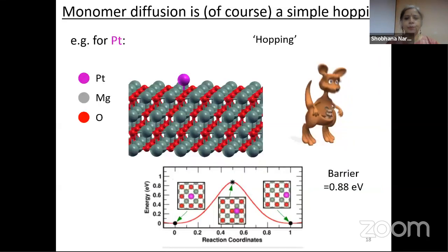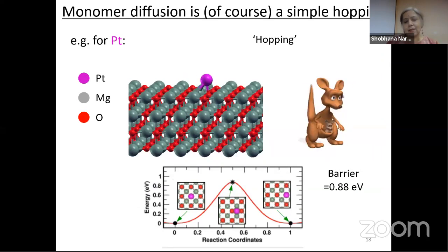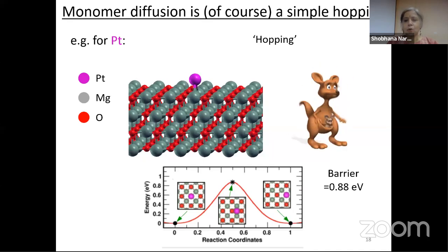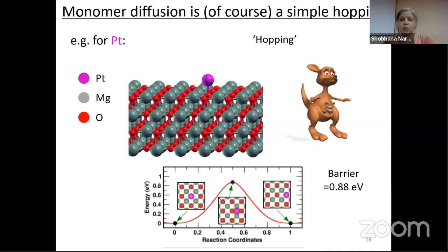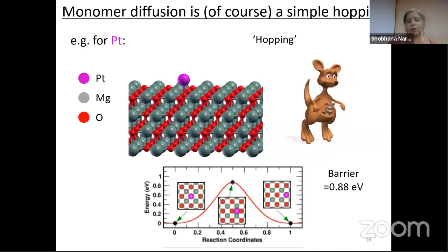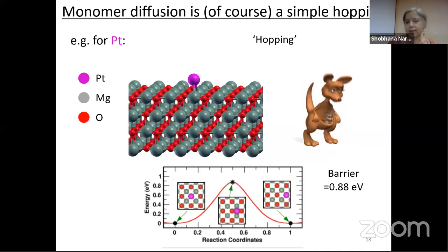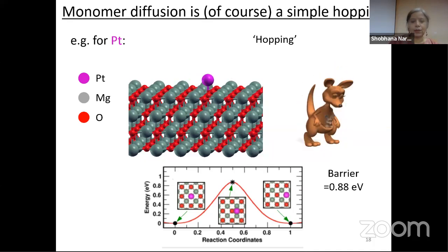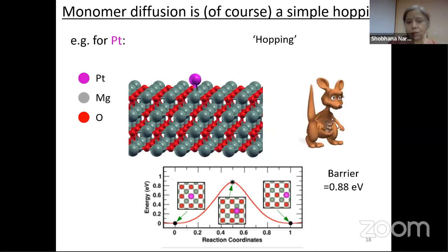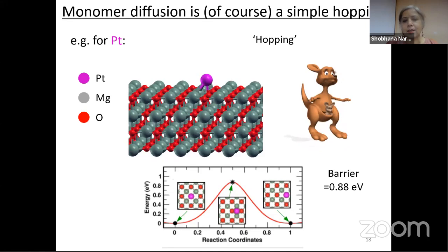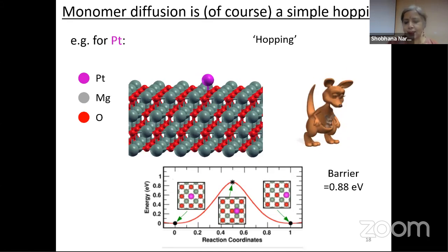Let me show you. So if you have a monomer, there's only one mechanism. That is a single atom of the metal on the substrate. It can only move by this process, which we call hopping. And you can calculate the diffusion barrier for this. This shows, for example, on the bottom panel, I've shown you how the diffusion barrier looks. There's nothing very surprising there.